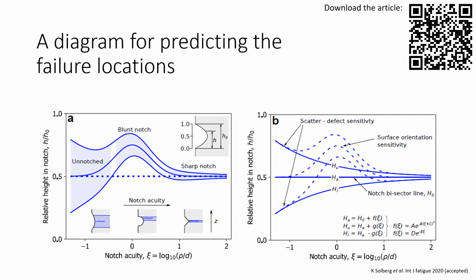The diagram is separated into 3 sections: unnotched, blunt notch, and sharp notch, where in the unnotched there are not a lot of very downward facing surface close to the minimum cross section, and the scatter is kind of distributed, while for a blunt notch we have a strong effect of the downskin region, while in the sharp notch, the notch is a stronger feature for initiating fatigue than the defects.